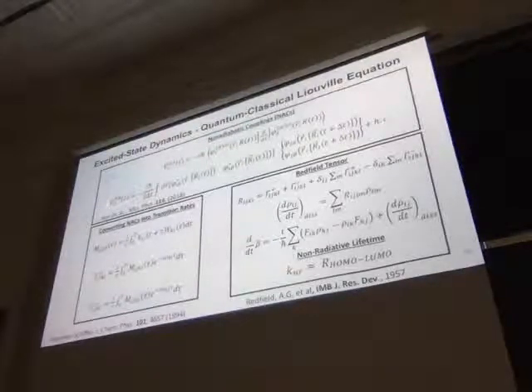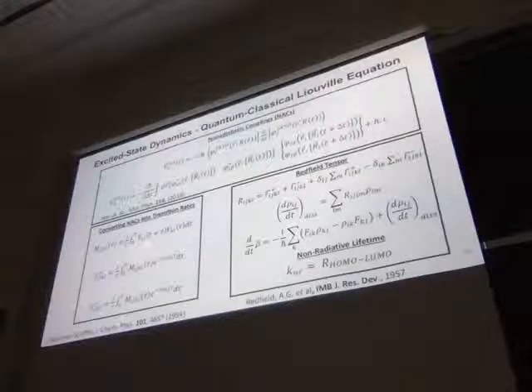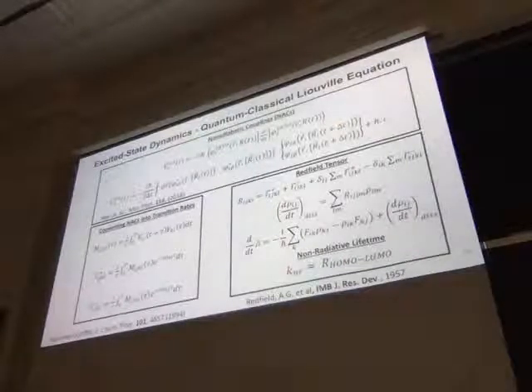To convert these non-adiabatic couplings into rates, we use a standard procedure of taking autocorrelation functions of the non-adiabatic couplings. You measure essentially how fast they decohere, and then you take Fourier transforms and convert them into rates. These rates we incorporate into what are called Redfield tensors. This is a density matrix theory that describes electron-phonon interactions and rates of heat dissipation. The Redfield tensor provides the dissipative transitions for the density matrix, and this is the time evolution of the density matrix from the Liouville equation. Another thing to note is for non-radiative lifetimes, we can approximate the non-radiative recombination as just the matrix element corresponding to the HOMO-LUMO transition, or whatever non-radiative transition we're looking for.